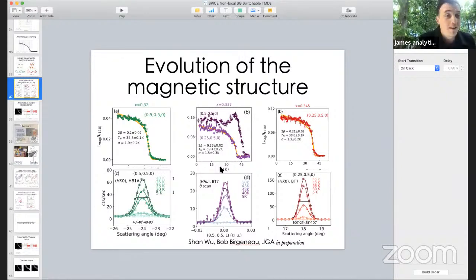Remember, I also showed you the heat capacity and the magnetization. We have the sharpest, the most delta-like heat capacity anomaly, the sharpest magnetization drop. So to me, it doesn't seem like there's magnetic disorder in these systems. It just seems that there are two order parameters.